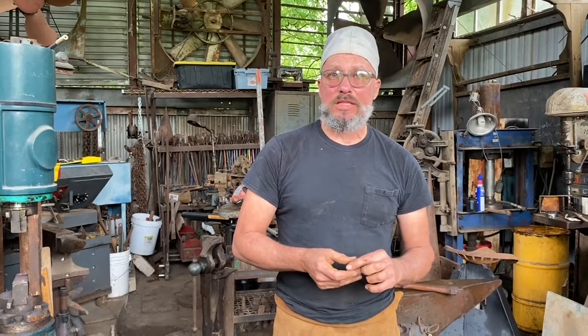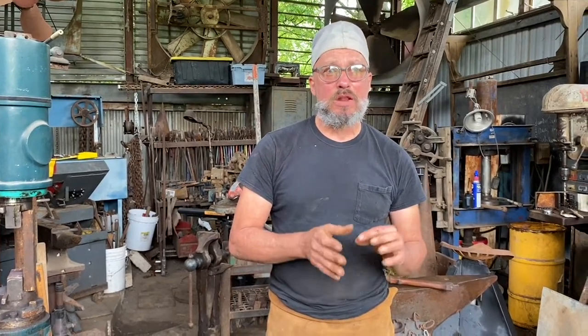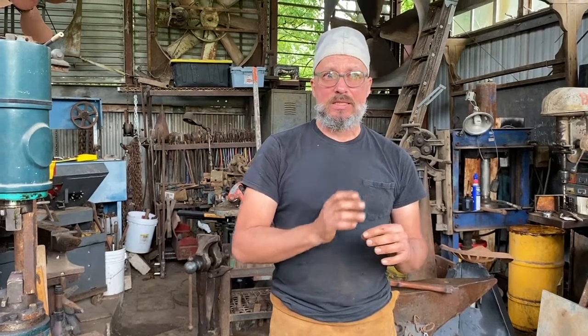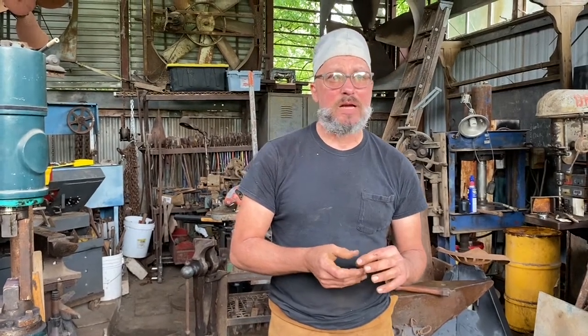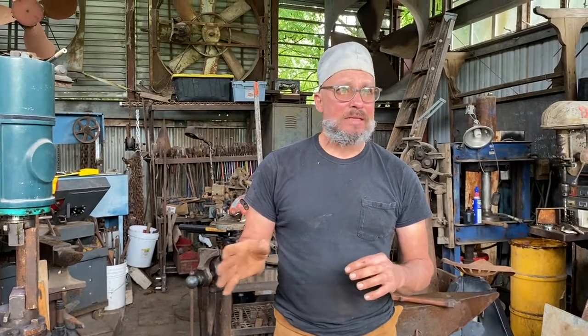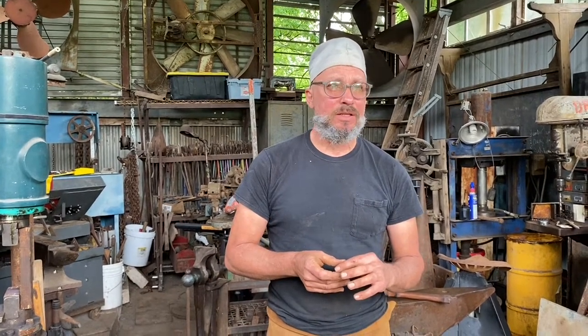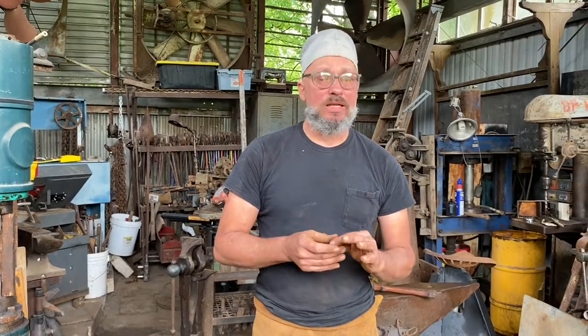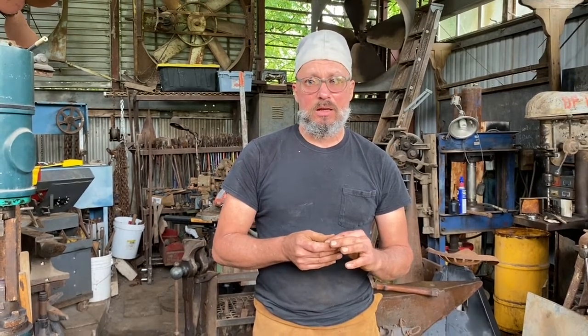Some bladesmiths call this packing, and I'm not afraid of working it right at that transition temperature. And like I said, 1450 for mild steel. You'd have to have a magnet to see when you get your magnetism. Typically, it drops a little bit below 1450 to get your magnetism when you're on the falling heat. When you're on the rising heat, it has to go a little bit higher than 1450 in order to become non-magnetic. You know what it feels like when it's above transformation temperature and it's still moving. Try not to forge it too far below that, but you can rationalize it through this concept of grain refinement and packing.